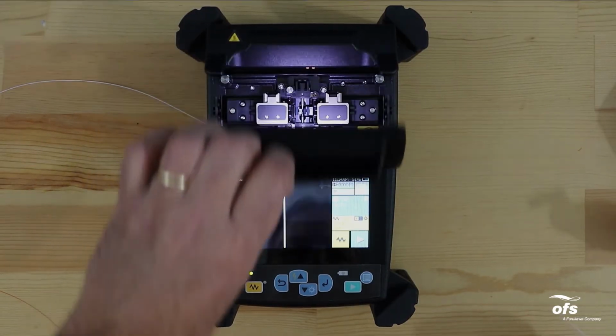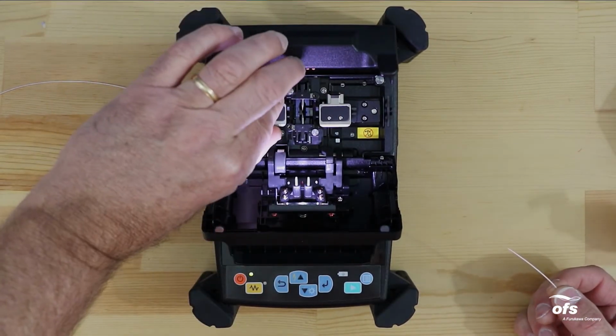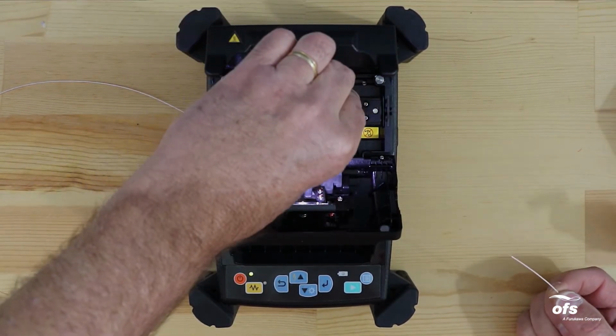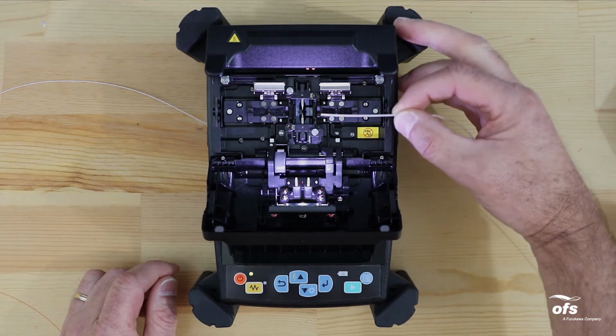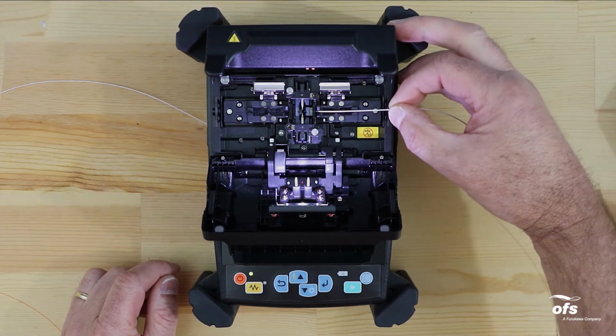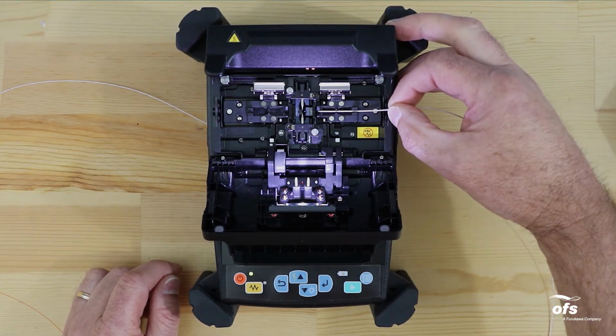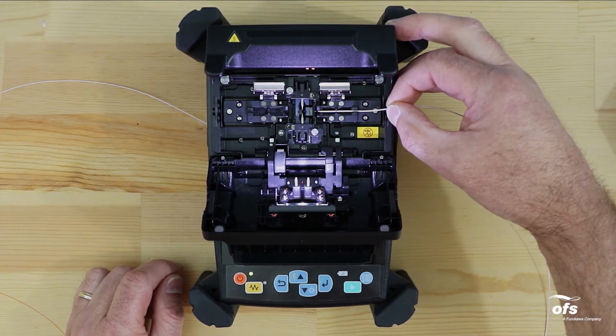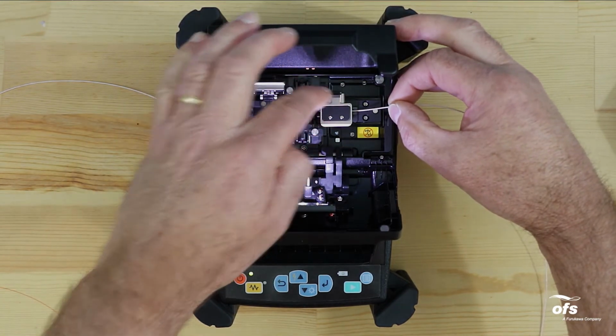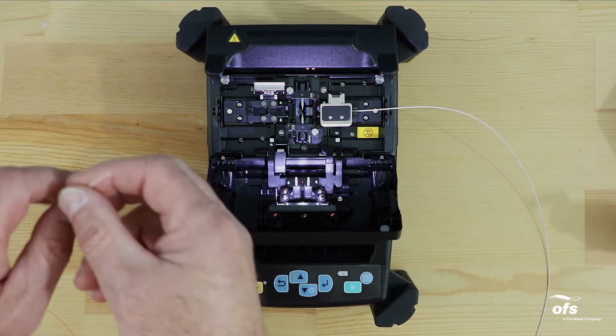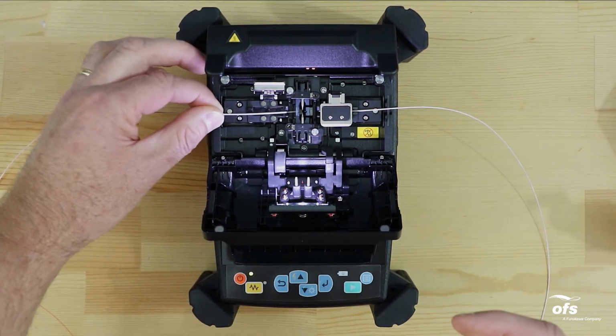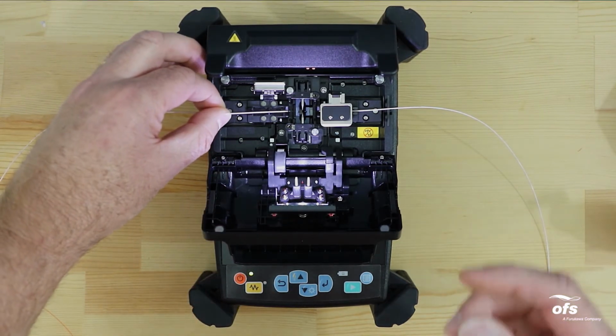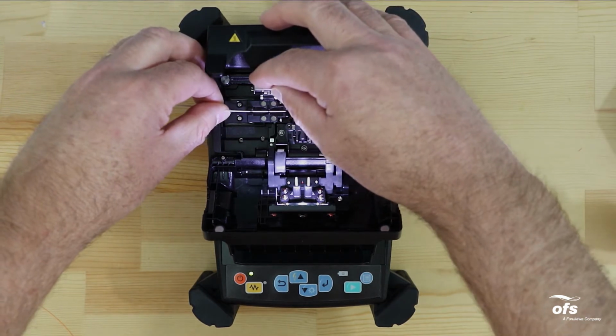Open Fusion Splicer windshield. Open the lids on the tight holders. Remove cleaved fiber from the cleaver and immediately place into the Fusion Splicer tight holder. Align fiber so the tip of the fiber is close to the center without going over center and that the fiber is aligned in the V groove. Secure fiber position by closing the tight holder lid. Repeat the procedure on the remaining fiber.